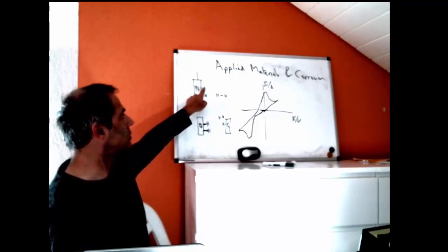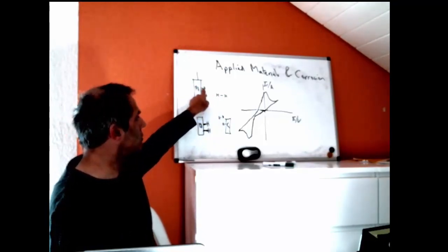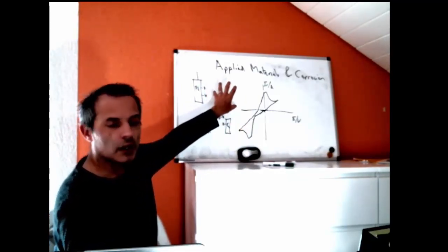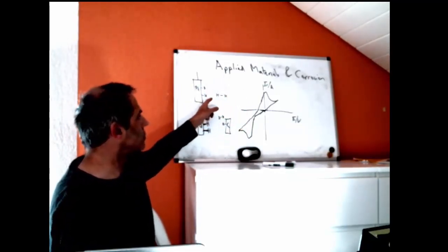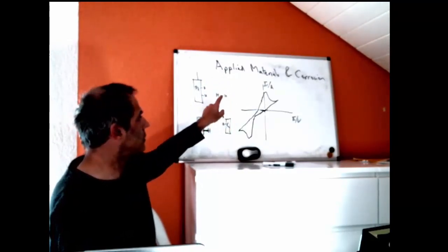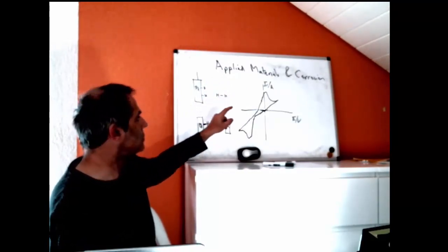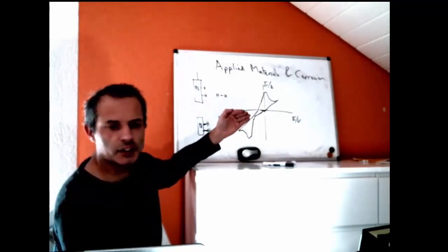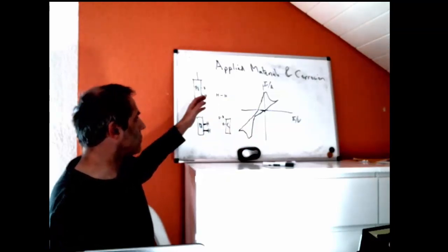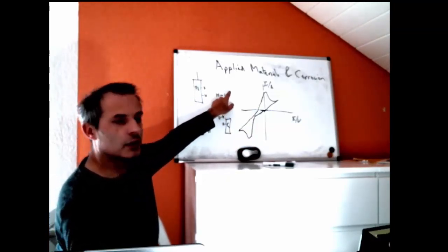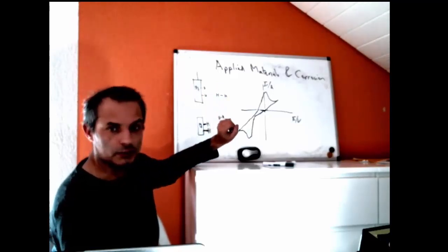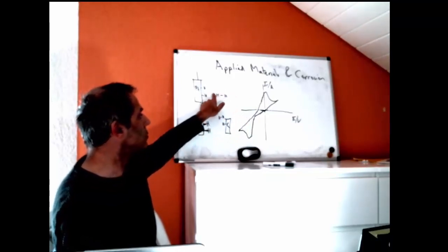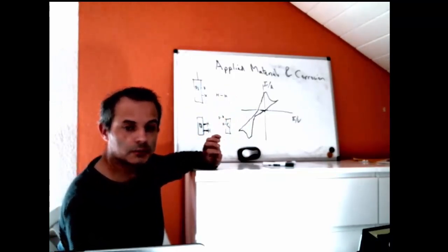The hydrogen sticks to the surface as singly bonded hydrogen, and it can interact better with a fatty acid molecule from the olive oil than it could if it was in the H2 state. That's because this bond effectively is broken in half, and the activation energy is half as big for the whole reaction, because our hydrogen is already broken. We've still got to break these bonds, but we've only got to break one at a time, whereas normally we would have to break both at once.